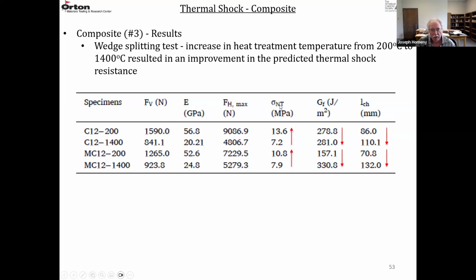So if we're looking at this tensile strength, it's much stronger at 200 than at 1400 degrees curing for both C12 and MC12. So it goes from, let's say, 7 and 7 at 1400, and this goes up to 13 and about 10 or 11 at 200.